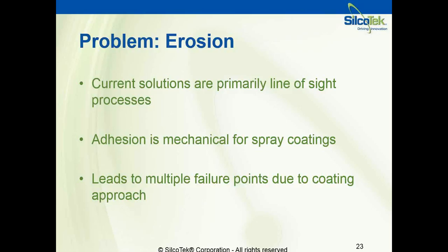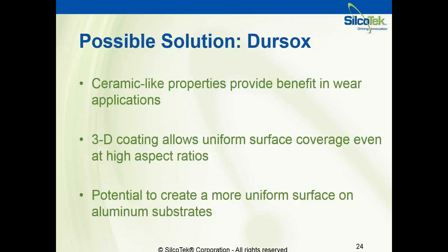And this is an adhesion or a bond that is mechanical with spray. So it's still strong, but it's not molecularly bonded. You can't flex it. It will flake if you flex. You can't bend it. It's not easy to be installed. Film stress at a high thickness really needs to be controlled. So there are a lot of issues, not even with the coating substrate, the coating surface itself, but the actual coating method that can lead to erosion and eventually contamination in the process stream down the line.